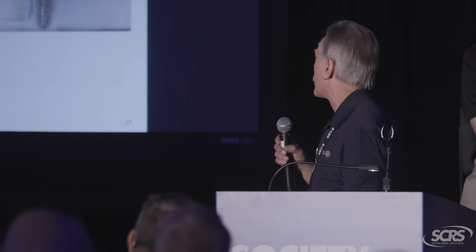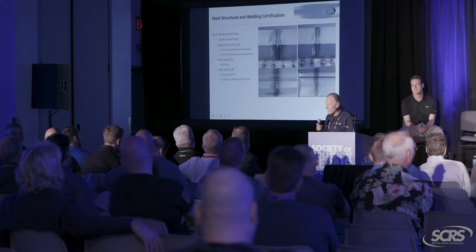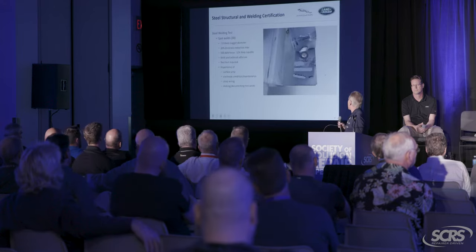A lot of techs go, I want to go around, right? No, you can't. You've got to stay right in the middle and pull the trigger, because you only have an instant while that weld is forming. If you move it, it deflects the focus of the heat too much and you get a bump on the back, I'm going to say a melt through. So you need a minimum of 0.5. That one's a little bit tricky as well. But anyway, that's it for that.